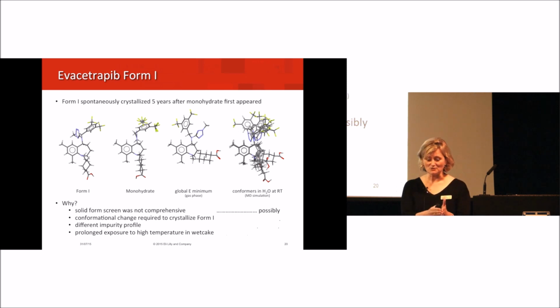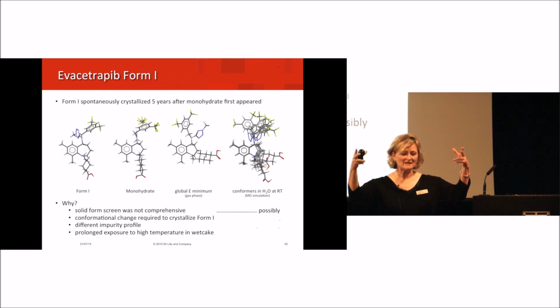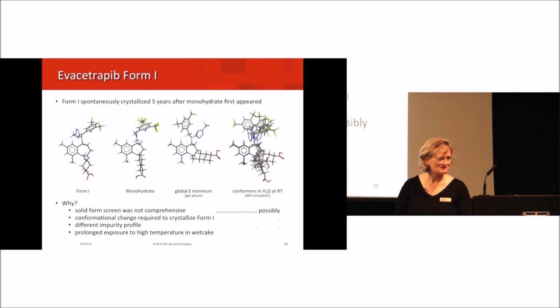But what I can tell you is in the course of the 6 or 7 years that we worked on the compound, it had been crystallized under similar conditions many, many times. How the new form appeared was a mechanical failure in production, which allowed the slurry to be held for a very prolonged period of time at all of 60 degrees. And that was what caused this material to happen. Is there a conformational change that was required? Well, I don't think so. I don't see this form 1 conformation being really that different from the monohydrate, and we've got other evidence that we're not perhaps limited by the molecular conformation.